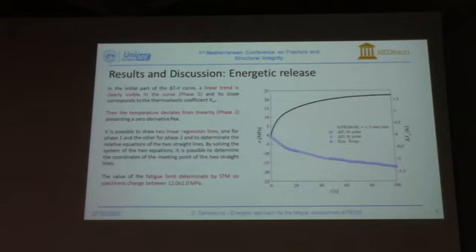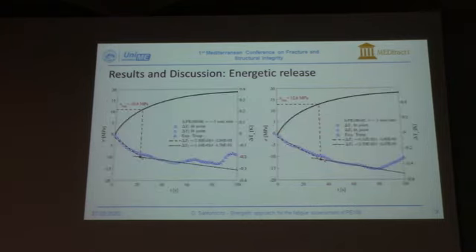So if we analyze the temperature trend during a static tensile test, we can clearly see a first linear decrement of the temperature, the second phase, and the third phase. If we make the linear regression of a set of points from phase 1 and phase 2 and take their intersection, we can read on the stress curve the value of the fatigue limit determined by the static thermographic method. For the 3 tests that we have performed, we obtained a value of 12 plus or minus 1 megapascal. Here is the trend of the other 2 tests, which essentially show the same trend.